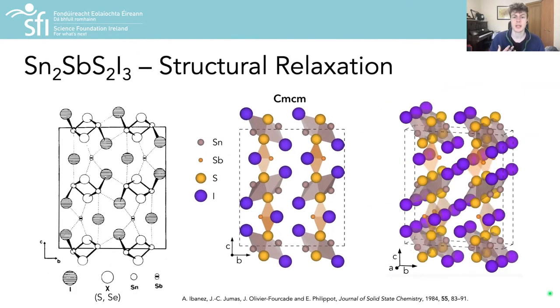The first step in a theoretical investigation of the material is typically to calculate your optimised crystal structure, from which you can then calculate the properties you are interested in, such as the electronic structure and optical absorption. For this we usually turn to databases like the ICSD or the Materials Project for a starting point or initial guess, and then relax with an appropriate DFT functional.